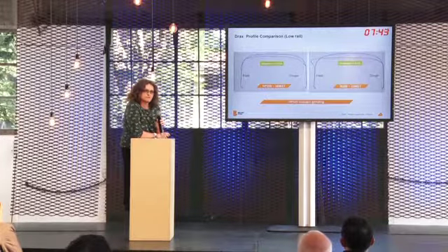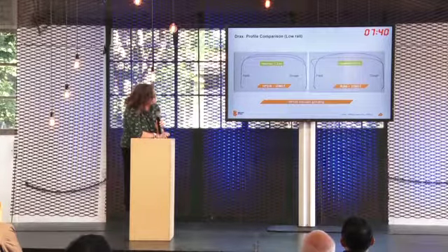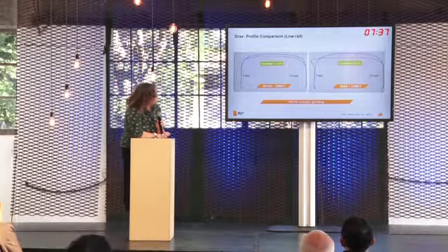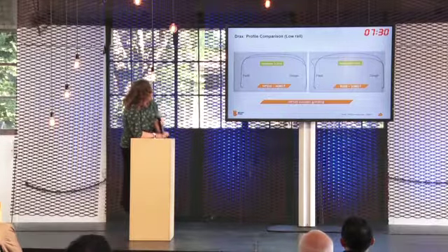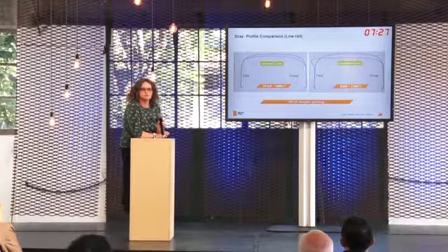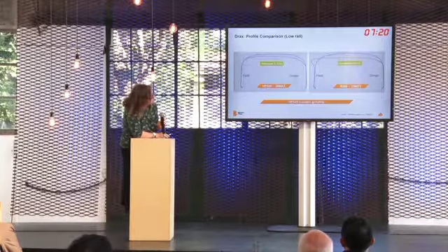So looking at the profiles, if you look at the right one, that's the R260. And you can see the measured rail profile is the red one. And you can see the low rail plastic flow. Head wear was 4.3 mil at that point. So if you look at the HP325, which is on the left, no plastic flow to be seen. So we've pretty much cured that problem from that particular site. Head wear at 2.2 mil, so half of what the R260 was, but bear in mind the HP325 does include the grinding. I don't have the grinding figures, the amount of material that they removed, to hand, but it is in the paper.